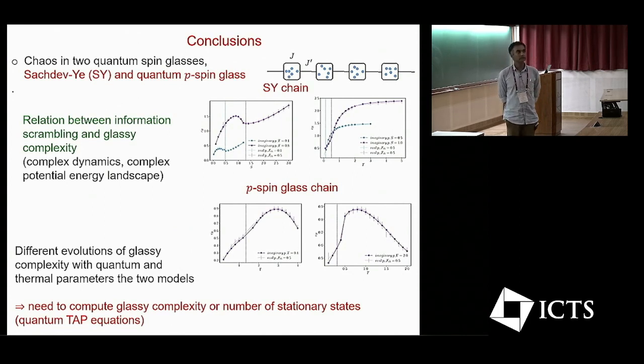About the difference in the usual transport in these two models, like the regular two-point spin-spin correlators? Yes, they are very similar. Both of these models, as I showed earlier, when you have this two-step relaxation onsetting, you see this maxima in the Lyapunov exponent. It turns out that the two-point correlations have very similar features: at high temperature they are simple exponentials, then you have a complex relaxation. From that perspective, these two models are not different. But if you look at the Lyapunov exponent and butterfly velocity, they seem to be different.